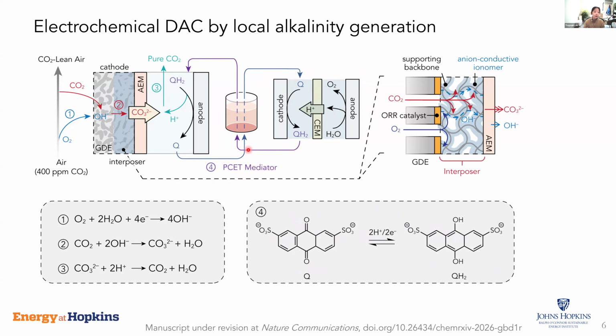And as we said, because of the low CO2 concentration in the air, what we really wanted to do is maximize the utilization efficiency of the hydroxide generated at the air electrode interface. So the unique invention of this work is to introduce this interposer layer, what we call, which is a three-dimensional layer that is porous, so the air can permeate through, but at the same time, it has anionic conductivity. So basically what it does is increase the residence time of this hydroxide in this interposer layer and give this hydroxide a little bit longer time to react with the dilute CO2 in the air before they get transported to the other side of the electrochemical cell and get released.